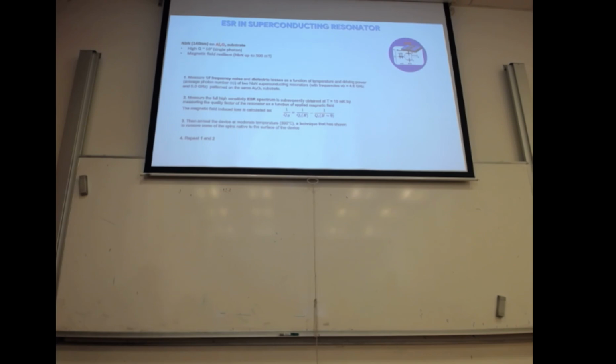So now there is a study that we did in the past year in collaboration with the group of Sebastian de Graaf. First of all, what was done in this study is that Sebastian built a very nice niobium nitride resonator on sapphire, and they are very high Q, single photon, and because of the geometry they are very magnetic-field resilient, up to 500 millitesla. And the idea was to try to understand a little bit more carefully what kind of spin species you have.